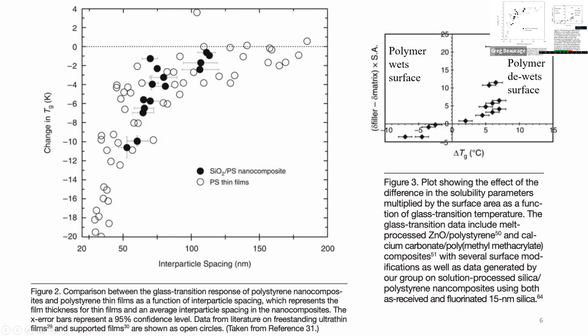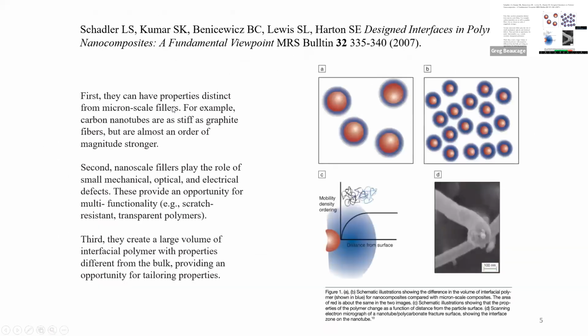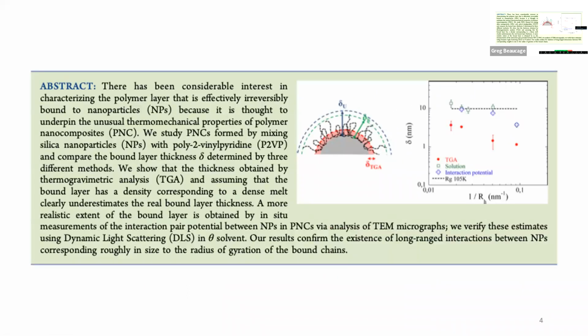So this was, I don't know what reference 31 was, but exactly the same thing was done in 1950 by a Russian guy by the name of Lipatov. He did a lot of polymer work, but basically there's nothing really new about knowing that the glass transition shifts when you put a lot of filler into the system. So in this case, with silica and polystyrene, it's a reduction in the glass transition. So that's an unfavorable situation. Right? And the same thing happens in a nanocomposite. The same thing happens in a composite. If you put in just bricks of silica, you get the same behavior. Right. So anyway, the Tg shift is one thing that people say is due to this bound rubber business. So you have the chains that are stuck to it.